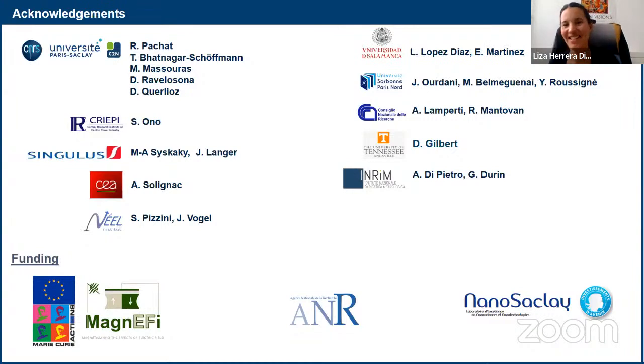Okay. Yes. First of all, the hafnium oxide that I've shown you on our films is done by our collaborators in Singulus, and they deposit typically 3 nanometers of hafnium oxide in situ by sputtering. So this hafnium oxide is not very good, let's say, in terms of electrical properties. So actually, we can very well bond across it or on top of it, and then access the metallic layer underneath when we want to do transport.